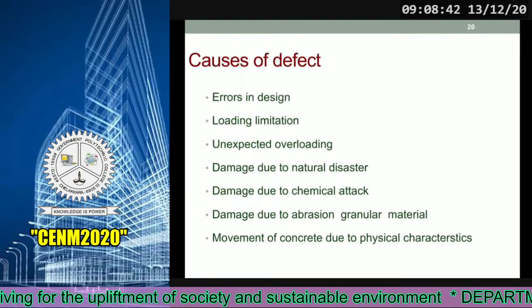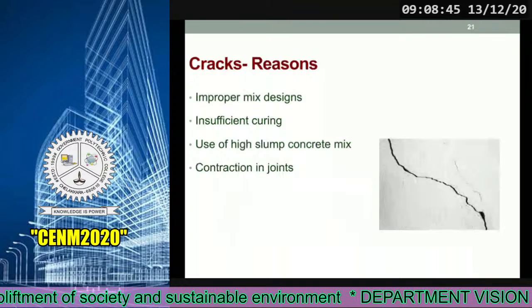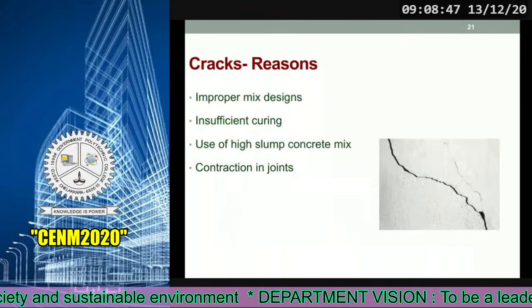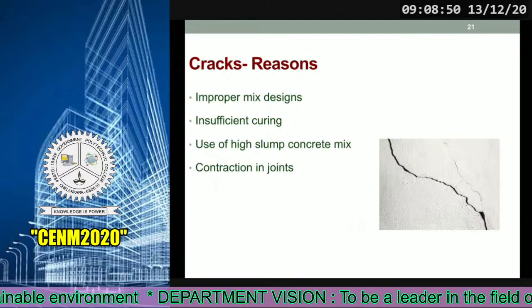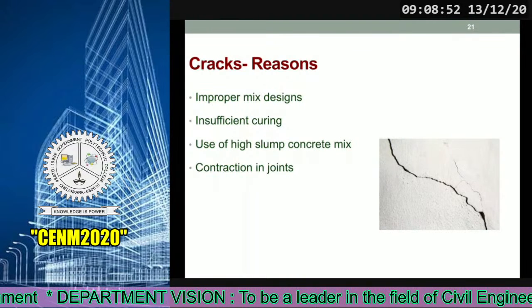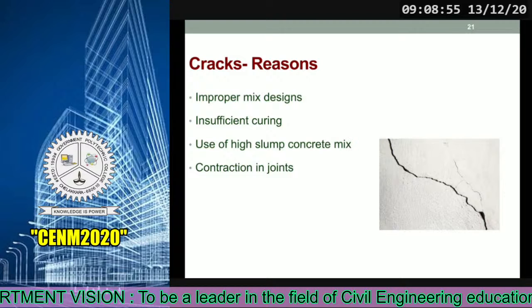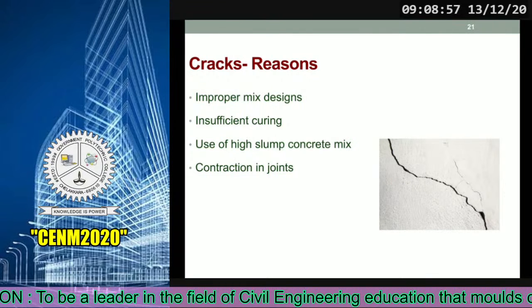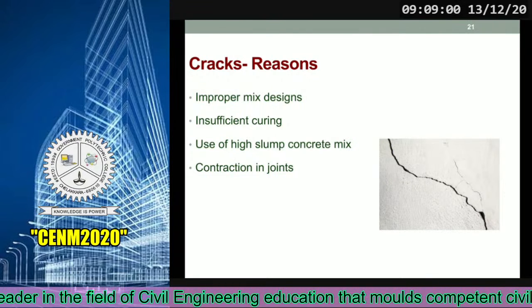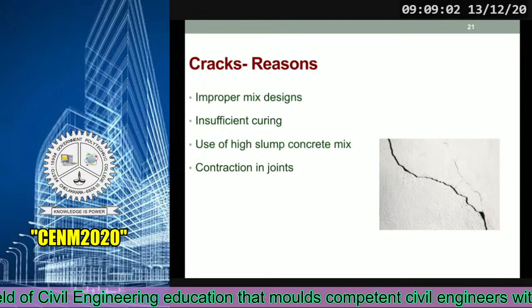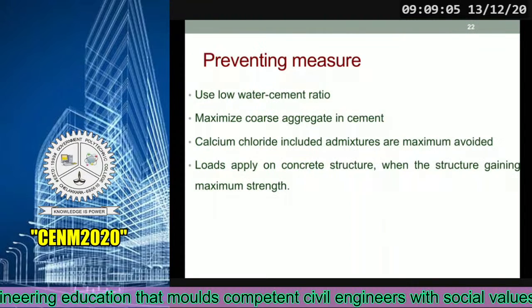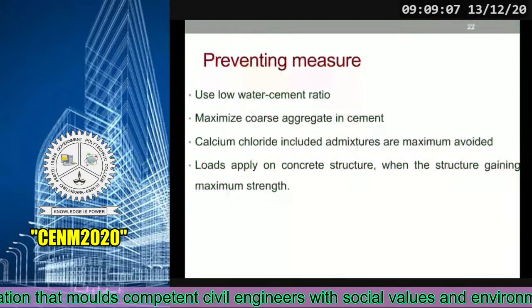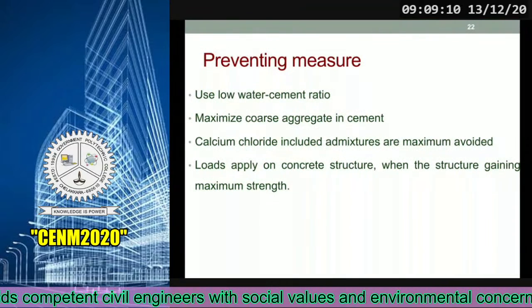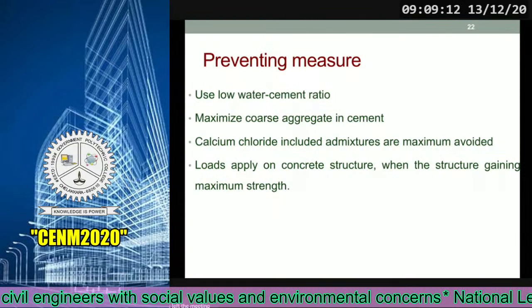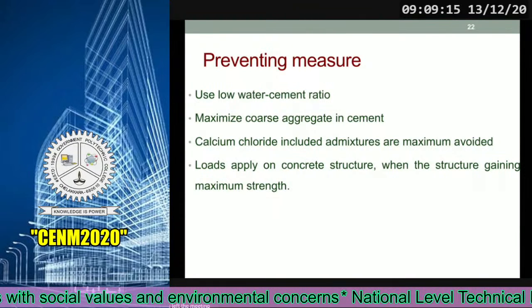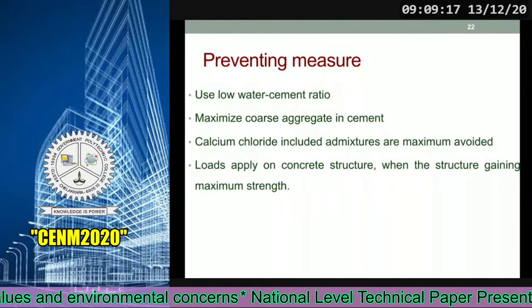And the first defect is cracking. Improper cracks are formed in concrete due to many reasons. If cracks are very deep, it is unsafe for the structure. Reasons for cracking are improper mix design, insufficient curing, use of high slump concrete mix, and contraction in joints. We can prevent it by using low water cement ratio, maximizing coarse aggregate in cement, avoiding calcium chloride included admixtures, and applying load on concrete structure when the structure has gained maximum strength.